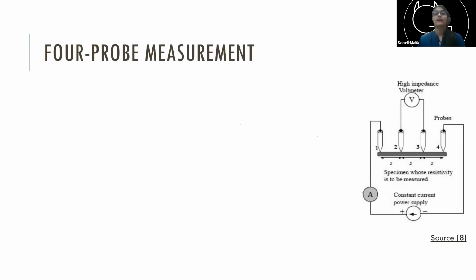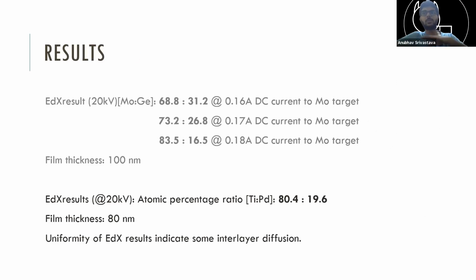Right. And how long does it take to generate one whole alloy? Okay, so sputtering, like I said, is a lengthy process. For any deposition that you do, you need to reach the place at least 6 hours before. If you need a good vacuum, you need to start your turbo pump. It takes 5 to 6 hours to reach a high vacuum. High vacuum is 10 to the power minus 6 torr or below. So that when you start depositing for sputtering, you can deposit for say half an hour or 40 minutes.